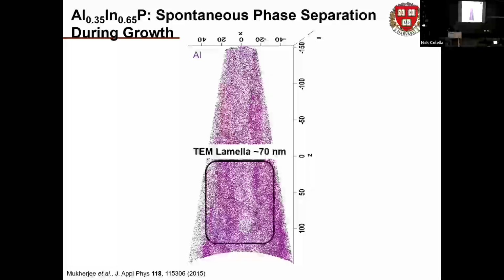The reason we couldn't see it in the TEM is that a TEM sample is a brick of material. It's about 70 nanometers thick, and you shine electrons through from one side to the other. And if you do that on something that has inhomogeneities on this sort of length scale, the few nanometer length scale, they all wash out. They all overlay with one another, and you don't really get anything. It's an averaged out result.